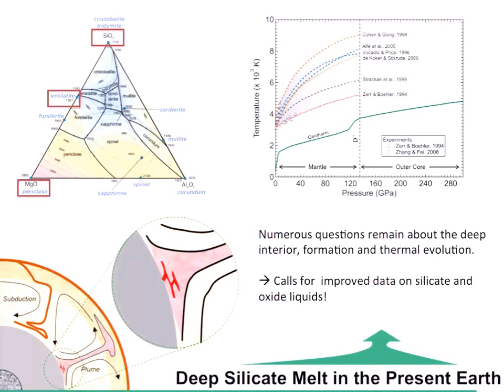A case in point: this is a phase diagram for MgO showing predictions for melting and some data from laser-heated diamond anvil cell experiments that were seeking to measure the melt curve. You can see there are 2 sets of experiments that are extremely discrepant, and then a number of calculated melt curves from theory that are also extremely discrepant by the time you get to the depth of the D double prime layer.